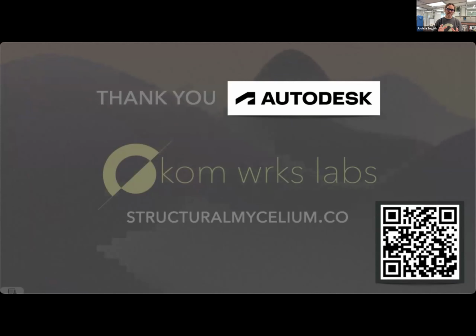As well, straight out of the box, our numbers for that 2-hour submersion test were about 10 times lower than the published data. I think that's because of the incredible density of the hyphal mat that we're growing in our parts, so there's much more surface area of fungus throughout our parts as opposed to the biomass that's in there from the discrete particles, in our case hemp hurd.